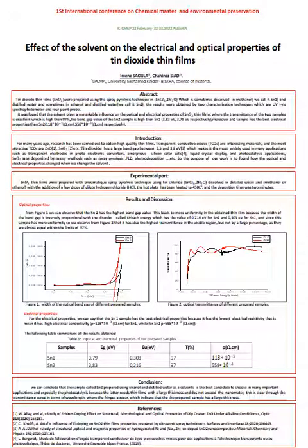Our samples were prepared using a pneumatic spray pyrolysis technique using tin chloride SnCl2·2H2O dissolved in distilled water and methanol, which we call SN1, or distilled water and ethanol, which we call SN2, with the addition of a few drops of HCl.